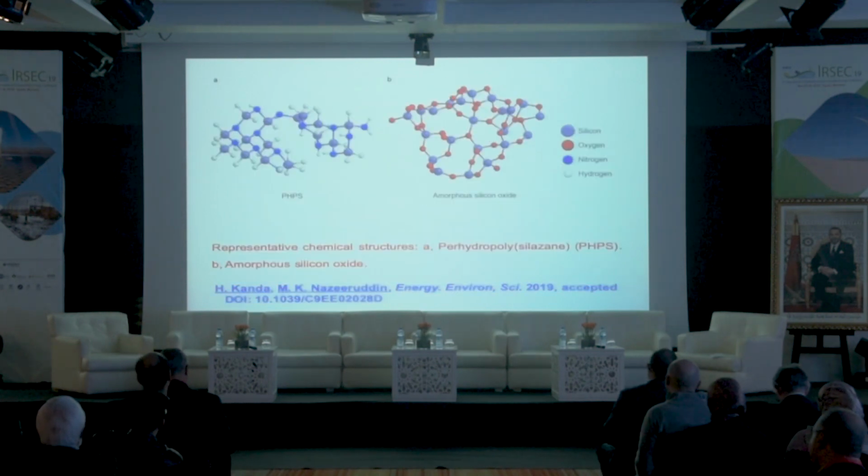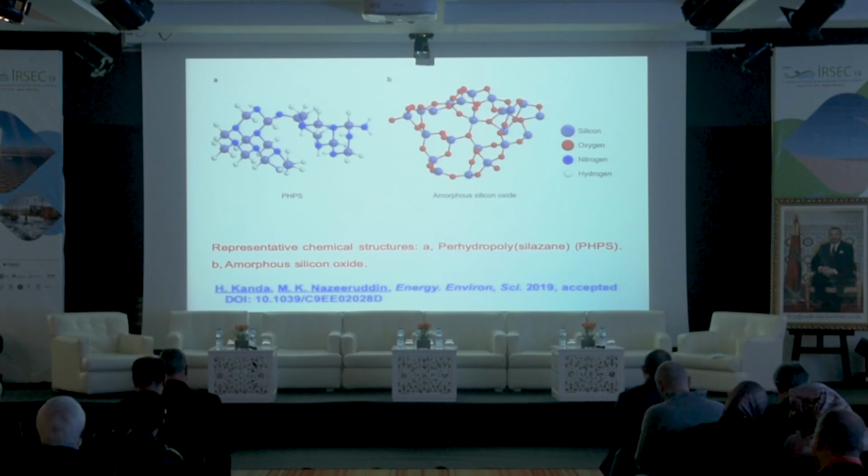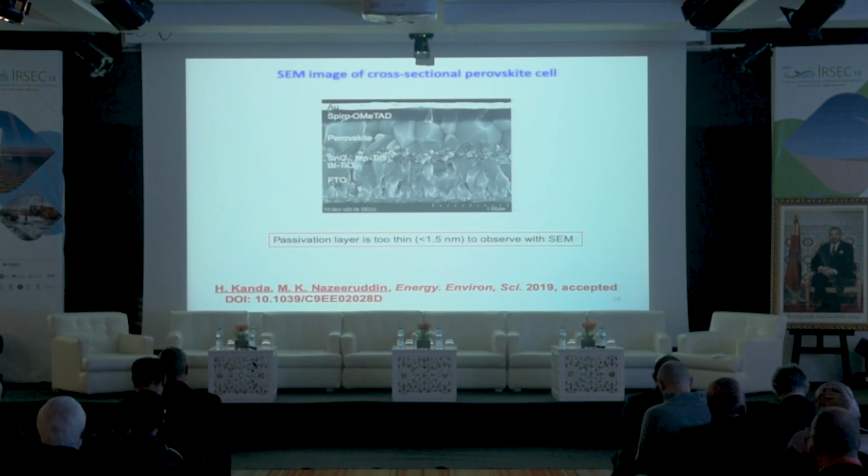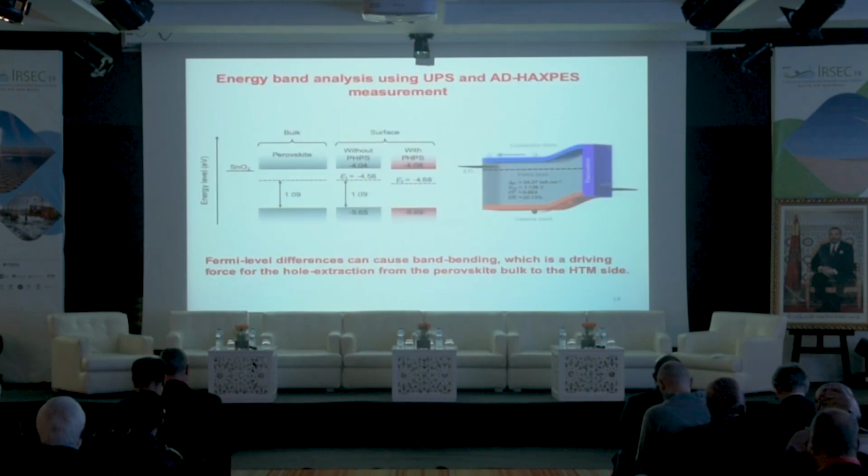This is PHPS. This is a silicon compound. When you react it with the perovskite, it forms amorphous silicon oxide on top of the perovskite. It's a very thin layer. You cannot see it even by SEM image. However, you can see the presence by different techniques.